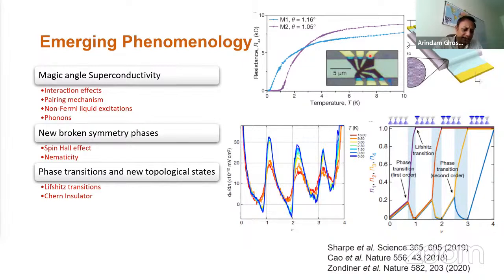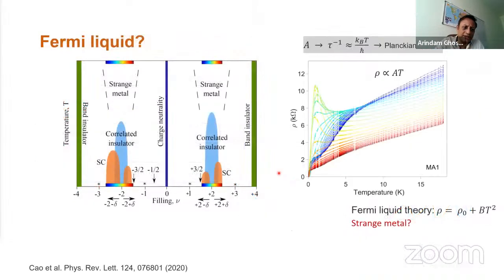One of the key questions, when the superconductivity was discovered in this twisted bilayer graphene, people asked what's the origin of the superconductivity. It is still under debate. There is no clear understanding of where the superconductivity comes from. But there were certain parallels that were drawn with high temperature superconductors. The reason behind it is the following. In these systems, the superconducting phase is often observed very next to what you call a correlated insulator phase. And this happens at the filling factor of 2.